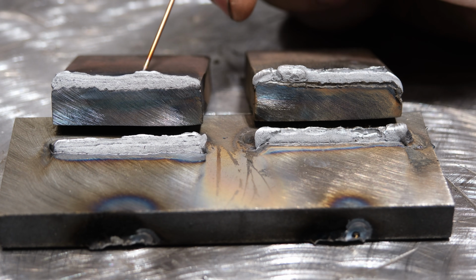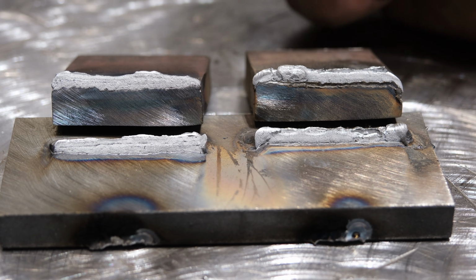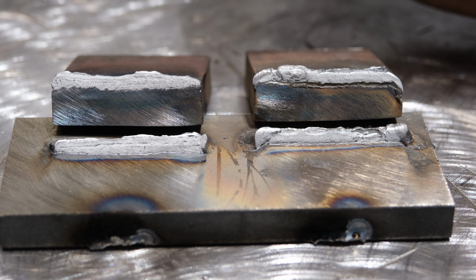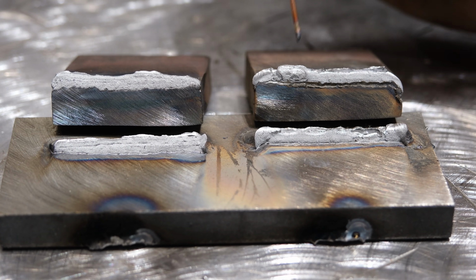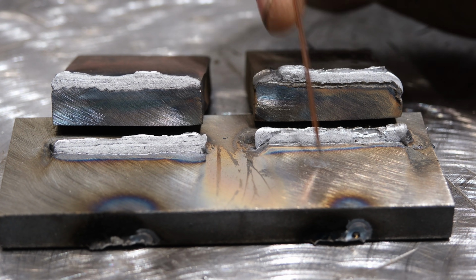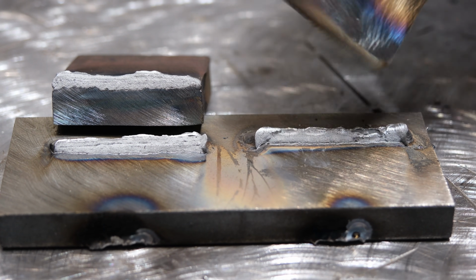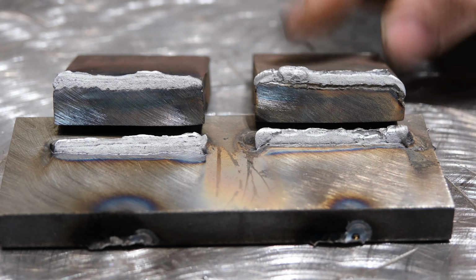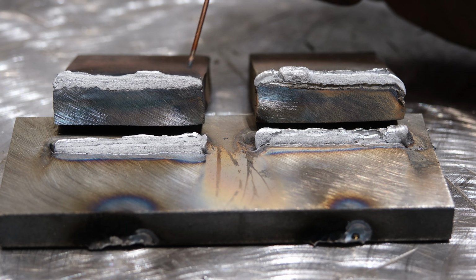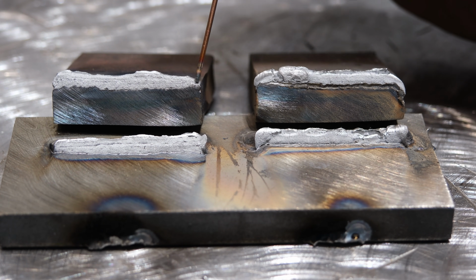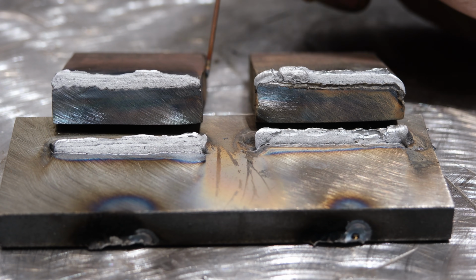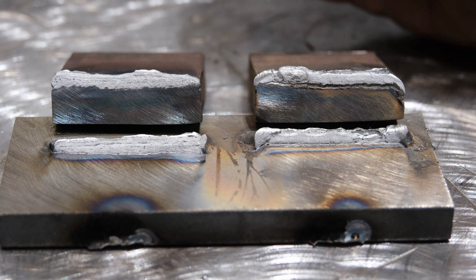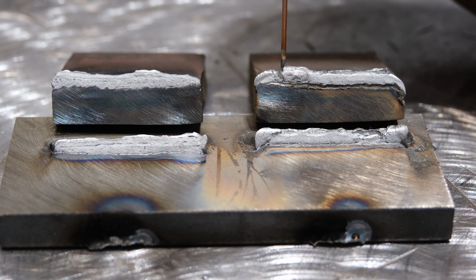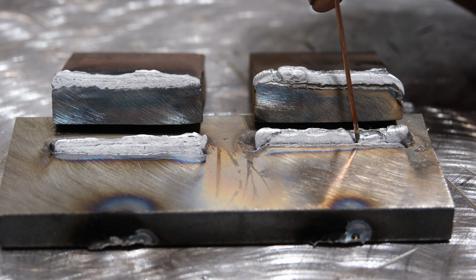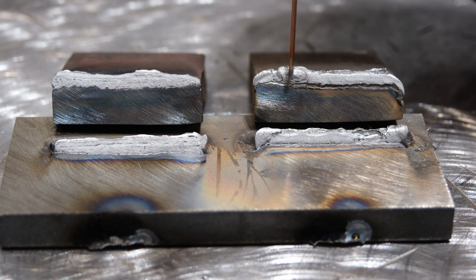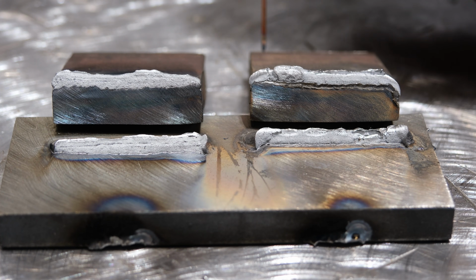So this is the TIG weld, this is a stick weld. I welded the stick from left to right, and because we're looking at the back side of this plate, the start was basically on the left here. The TIG, the start is on your right. So these two are the starts. Let's look at the stick weld. Much as I suspected, if you see this right here where it pulled out of the bottom plate, this is due to a lack of fusion.